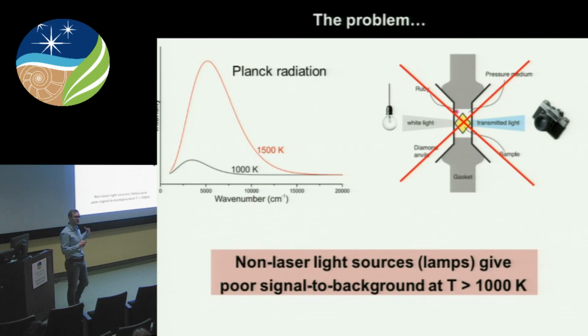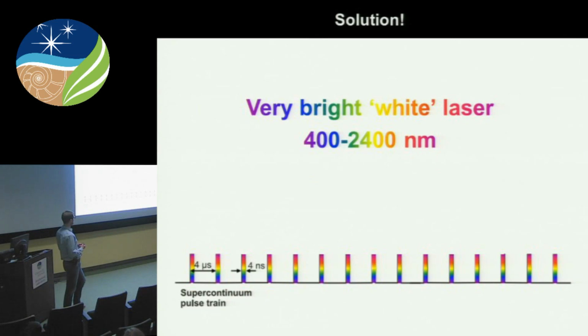But you may argue here that the lower mantle is not at 300 K, of course. And we would like to collect absorption spectra not at room temperature, but at high temperature. And here is a problem. Once you heat your sample to temperatures above 1,000 Kelvin, well, it doesn't matter what temperature, you will get intense Planck body radiation. And the hotter you heat your samples, the more intense the radiation is, and it also moves towards the visible range. So at high temperature, at some point, your Planck radiation will dominate the signal, and you will end up having a very poor signal to background ratio. Therefore, this method hasn't really been used at temperatures above 1,000 Kelvin.